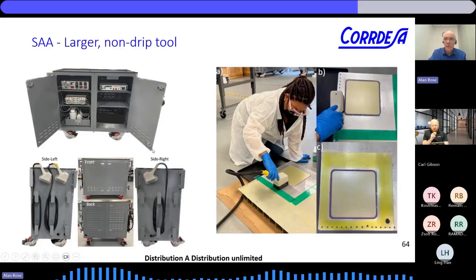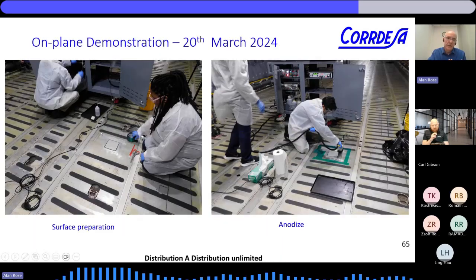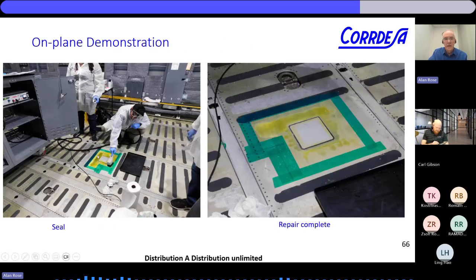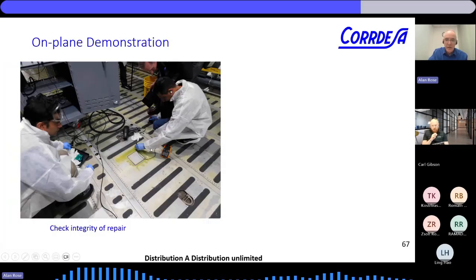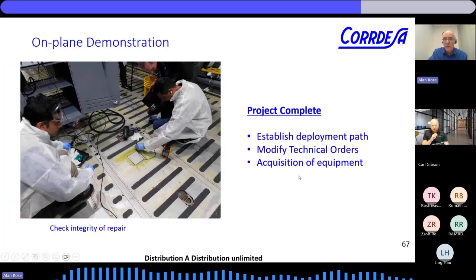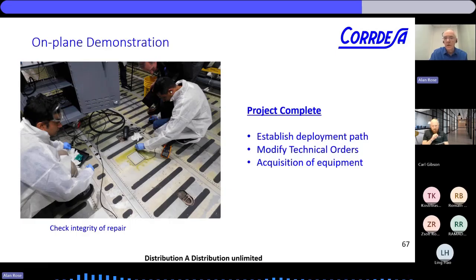We created this equipment, we tested it on real pieces in the lab, and then we actually went on a C5 Galaxy during the repair process, did the prep in situ, the anodize, the seal, and we have a complete repair, checking the integrity of the repair. So now the standards, the tech orders are being changed in order to accommodate this solution of anodize repair on the asset.